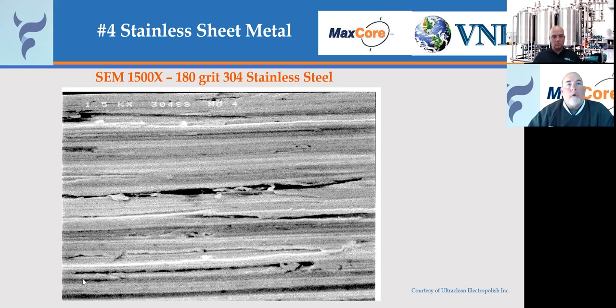As we're going across and we're mechanically polishing this and we're removing this dust and this debris from the surface of the steel, all that grinding dust that you're leaving on the surface that's getting down into these grooves of the material that's being folded over and trapped over top of itself is 64% iron, loose iron that could become contaminated and become mobile within the system if it's not removed.